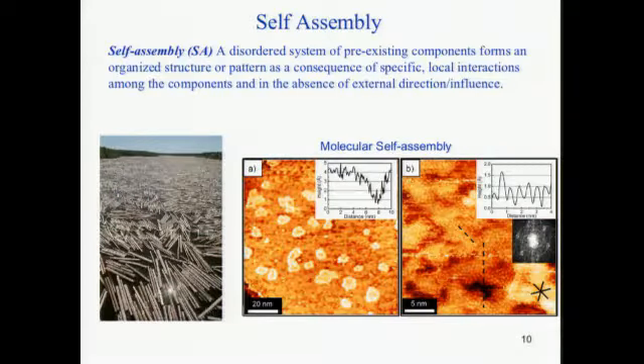And you can see one thing about them is that the logs are pretty uniform in size, and that's a big part of how self-assembly works. You're using molecules, or materials, that are very much alike. And because of that, they want to form a crystallized structure. Now, on a molecular scale, this is called molecular self-assembly. This happens to be biphenyl thiol. And if you are not used to looking at scanning probe microscope or scanning tunneling microscope images, you may not notice it, but there is order here. There's order in the structure by making this monolayer of biphenyl thiol.